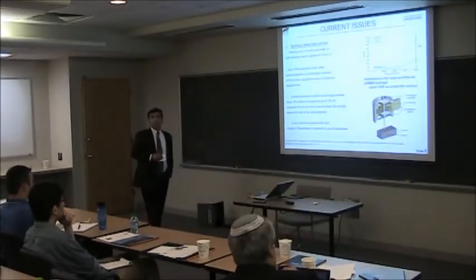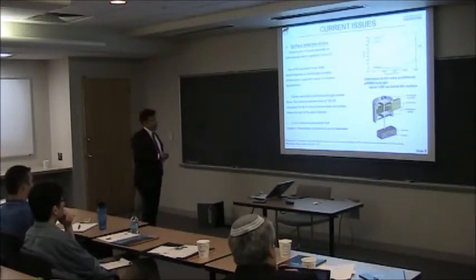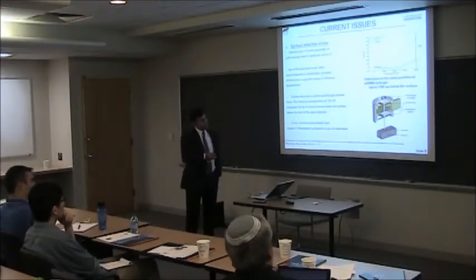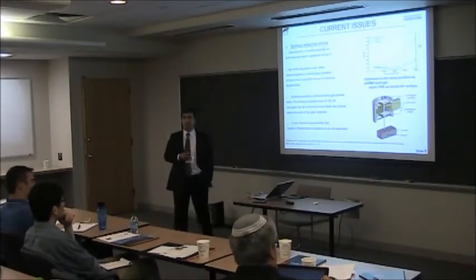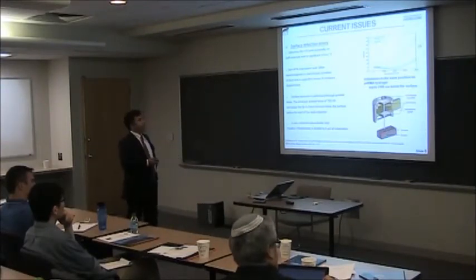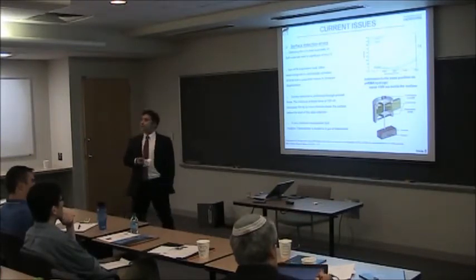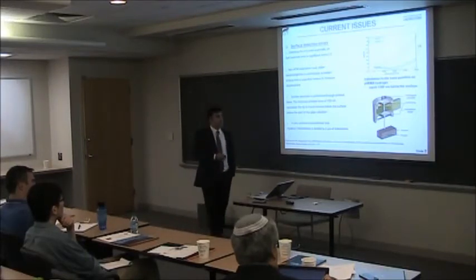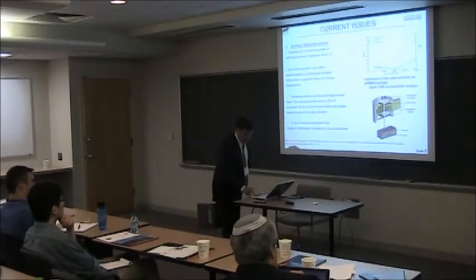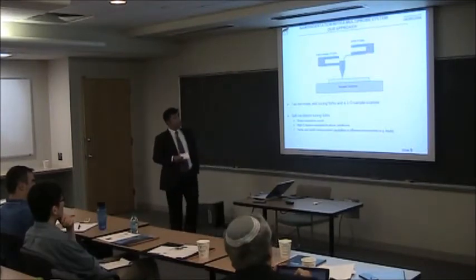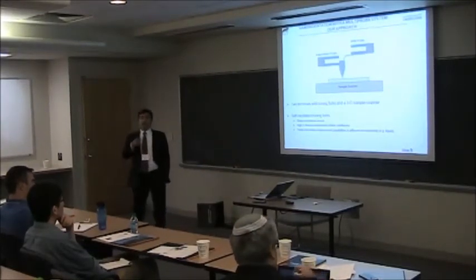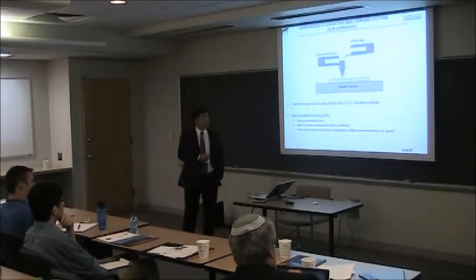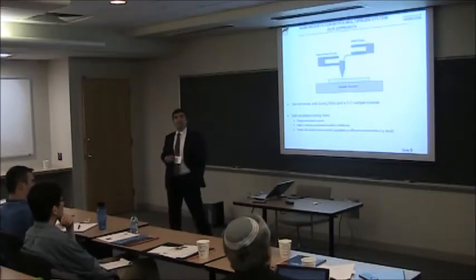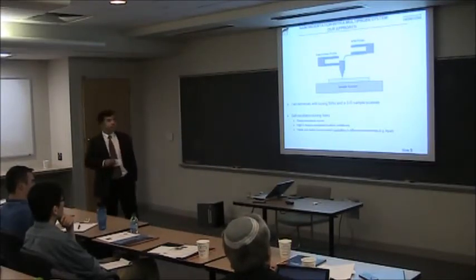There are non-AFM methods as well, where you have mechanisms to apply force and also measure the force. But then the problem with these is the contact point, the z equal to 0 point, it's not clear. If it's not clear, then your experiments are not repeatable again. So, as I said, we want to make sure that our system is producing good force calculations through the indentation probe, and also getting good distance measurements from the AFM probe.